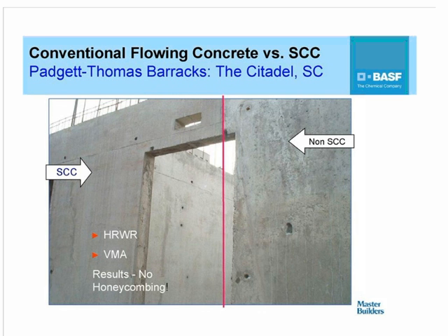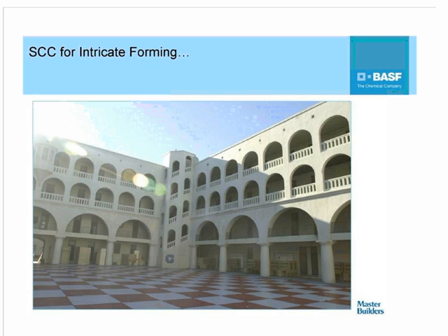Now, in this particular photograph, this was a project that was done in South Carolina, the Citadel, and it shows on the right-hand side of the picture 7-inch slump concrete vibrated in place, the non-SCC, versus self-consolidating concrete that was applied without any vibration whatsoever. And I think the picture basically tells the story. With self-consolidating concrete, the surface finish can be significantly enhanced, and sharper edges can result, even though the concrete may not be vibrated. And on this particular project, where we had a lot of architectural details, the use of self-consolidating concrete resulted in extremely good finish in the final structure.